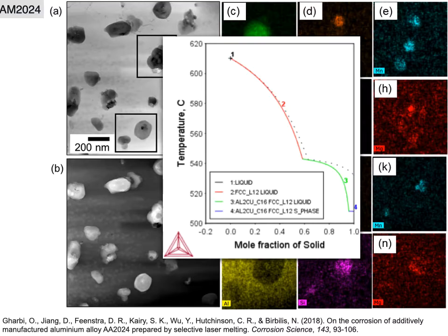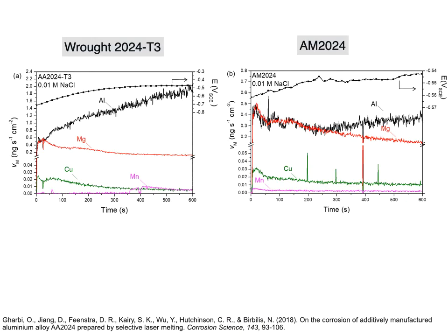as you can see here. So the 3D printed 2024 actually has a solidification microstructure, and that reveals to us that the first phase to form upon solidification, which is not S phase, but a theta variant, is retained. The corrosion rates of additively manufactured 2024 are much lower than those of wrought 2024, and this is attributed to the annihilation of constituent particles as localized corrosion sites. Also the refinement of the hardening phase.